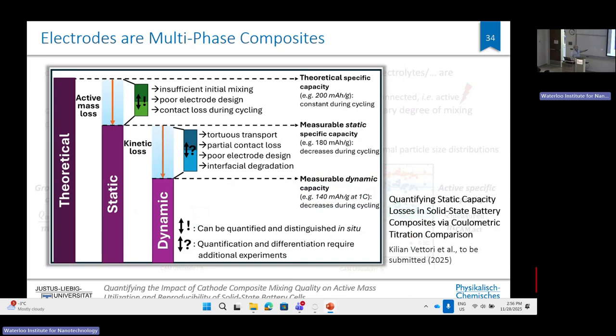So there's a theoretical active mass of your cathode material. And there is always some loss of material due to the fact that not everything is properly connected. Let's call that static loss of capacity. If you account for that, then there is a remaining loss, and that's the kinetic loss. Only that is the kinetic loss. If you don't account for that, you will think you have a much bigger kinetic loss in your system, because you would then simply add both together. But you have to separate these, and then you have a much better judgment of the quality and mixing of your cathode.